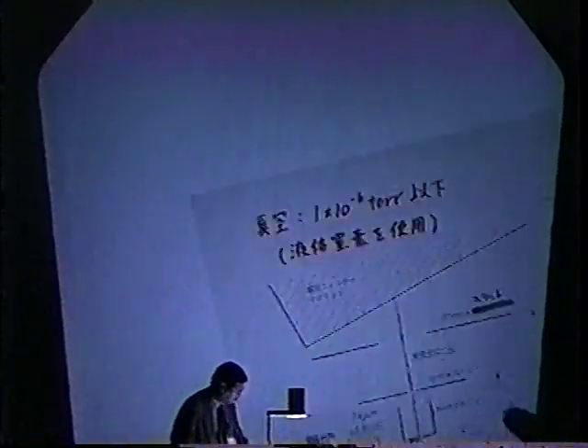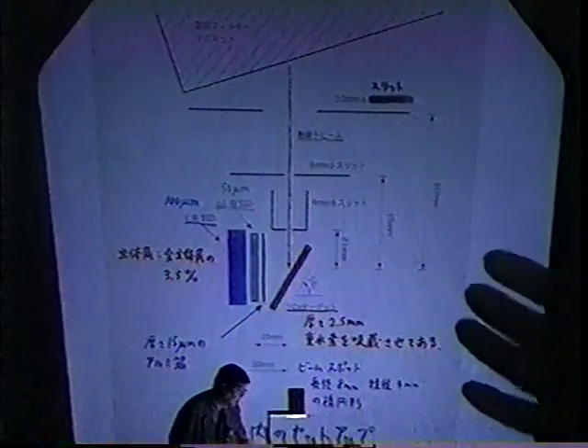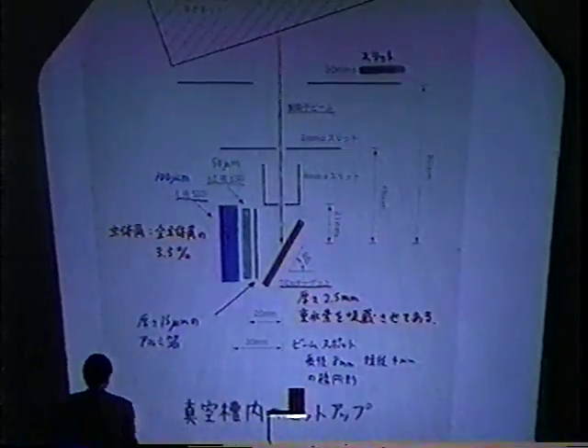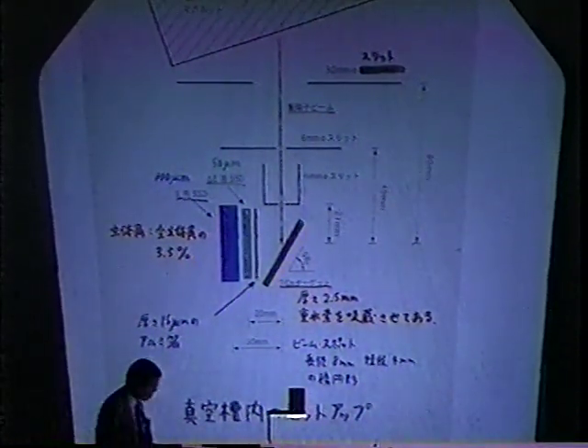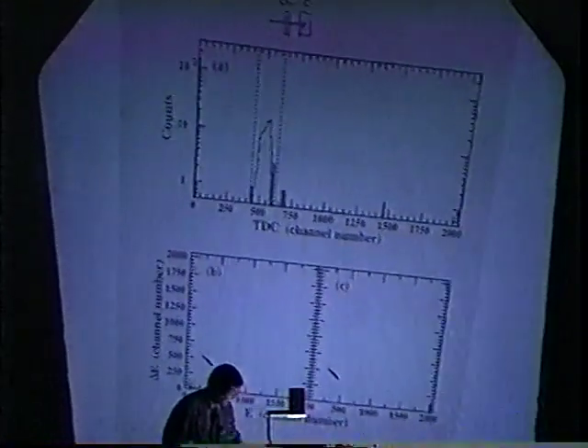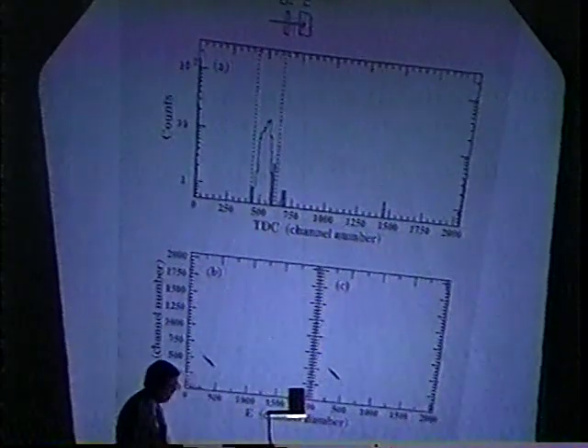And then we should take delta E measurement if we want to go down more. So we put the 2 silicon surface barrier detectors, one is a transmission type, which has thickness of 50 micrometer, and behind it is another thin 100 micrometer silicon detector. By using this delta E technique, we can have a very nice spectrum without any electric noise.